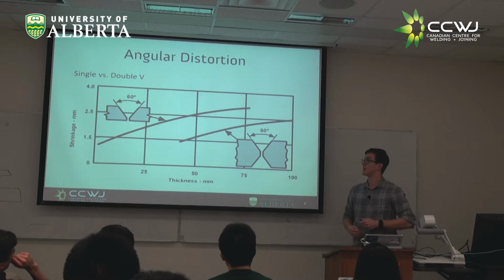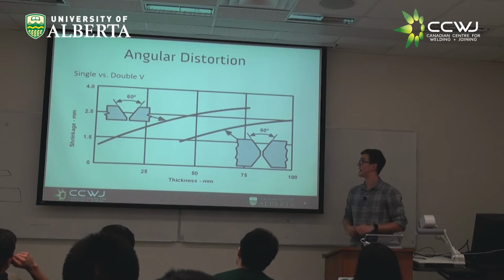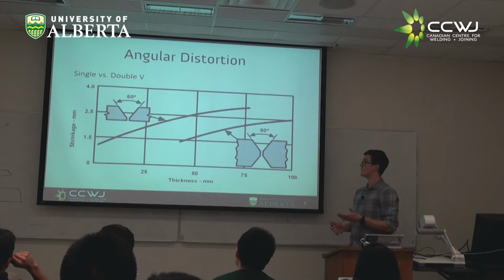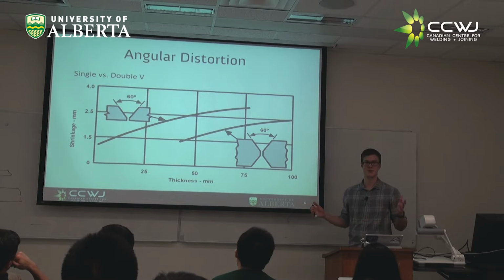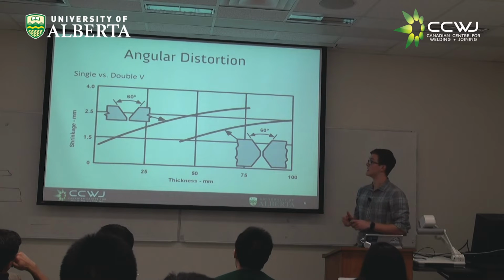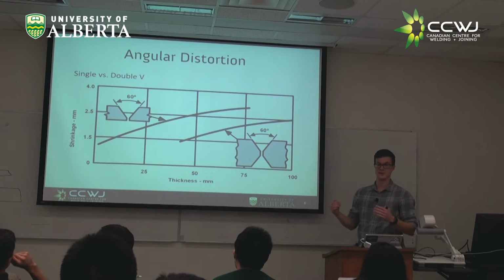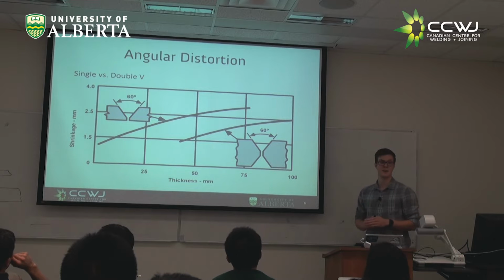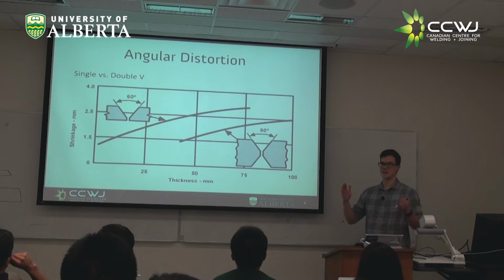So if you look at the effect of different joint prep, you can imagine that some joints are actually going to be more desirable for reducing that angular distortion than others. If you have a standard 60-degree bevel and you're only welding from one side, each pass you create is going to produce more and more angular distortion. In comparison, if you have a 60-degree bevel where you split from both sides, now if you weld from one side, you get some distortion, some stress, but you flip it and you weld from the other side, you're reducing some of that distortion.